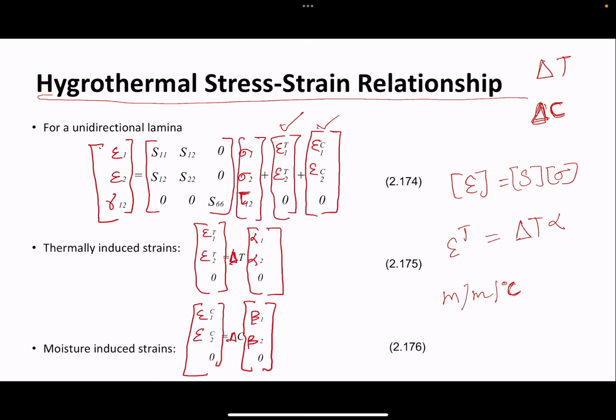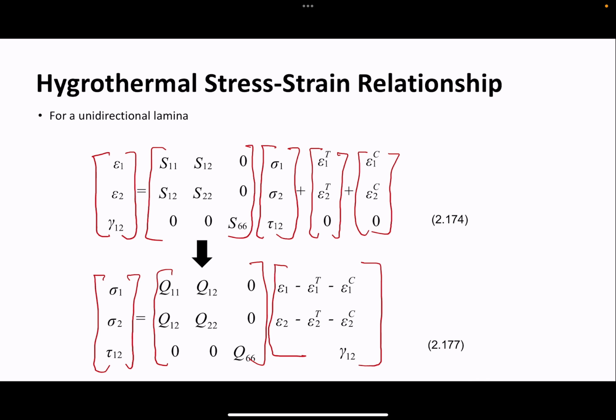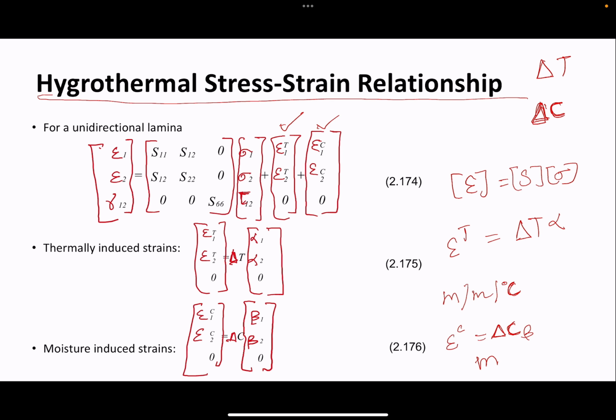And similarly, you have moisture induced strains. So moisture induced strains, epsilon C, it's the same thing. The amount of moisture absorbed multiplied by, what is this called? The symbol, of course, you know, alpha and beta. Beta is just the moisture expansion coefficient. To be exact, linear coefficient of moisture expansion. So it is the change in linear dimension of a body again per unit length, but here it's per unit change in weight of moisture content per unit weight of the body. So the unit is meter per meter per kg per kg. All right. So this is how the thermally induced strains and moisture induced strains are defined.